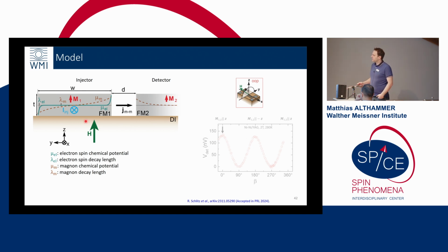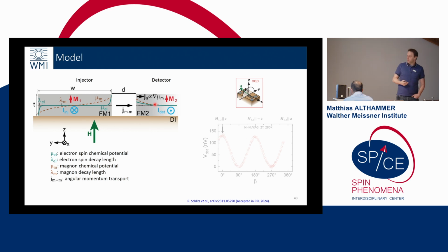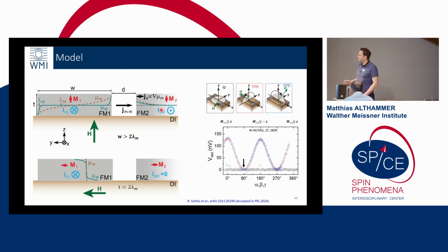And now there's a process, as we will shortly discuss, that can be either dipolar coupling effects over this short gap here, or the other way would be a magnonic transport down here that will lead to this magnon accumulation being transported over to the right-hand side, and then it will decay into the system. But since there is an accumulation here, it will again give rise to a spin current, and this can be transformed to the electronic state via the inverse process that happened on the left-hand side. This will give you a finite signal in the system, so you will get a detector signal.